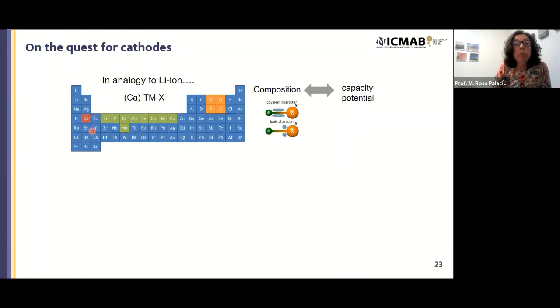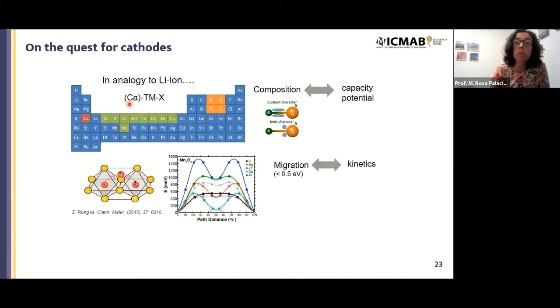This is our playground. Essentially what determines the theoretical capacity and the potential is the composition of the compound: which is the transition metal, the redox center, which are the counter ions, and the covalent or ionic character of this bonding. We can look for compounds having or not having calcium in the crystal structure, because we have calcium metal in the anode. So this is the source of calcium. It's not as in the case of lithium-ion technology, where lithium needs to be supplied by, for instance, the positive electrode.